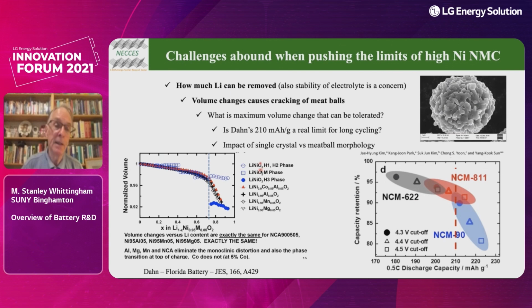So you can see here, this is his data from a couple of years ago. And it doesn't matter whether you substitute these materials or not. If the pure nickel compound, you get a two-phase reaction here. By substituting it, you avoid the two-phase region for the volume.